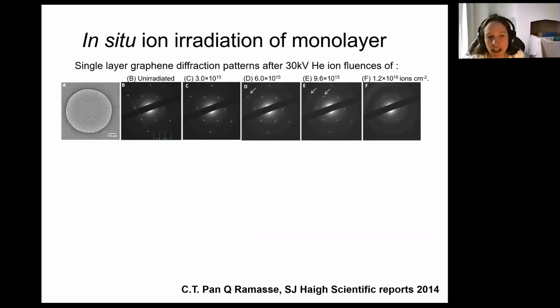An example of an experiment we did with this microscope is shown here. We took a single monolayer graphene sheet, and you get the typical diffraction pattern when it's unirradiated, and you can see that it's relatively pristine, although with some junk on the surface. As you irradiate that with the ion column, you can see in the electron beam that you start to get streaking. Actually, you can irradiate it with an awful lot of ions before you start to get streaking. It's a relatively robust material, and this was part of an interest from the Defense Threat Reduction Agency in the US in radiation-hard electronics.